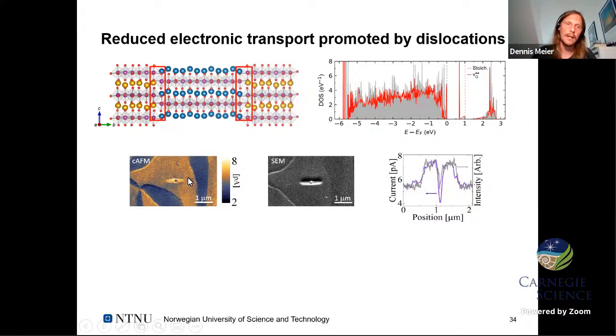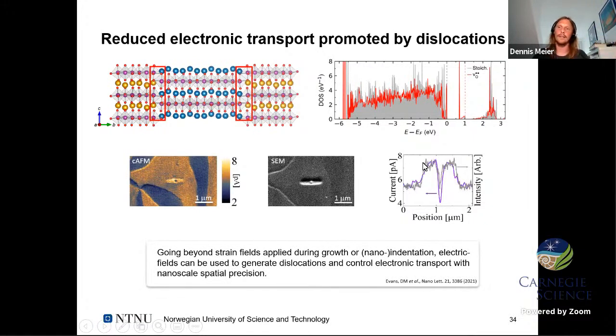And you can really see that when we now put an AFM tip, induce our dislocation or area with a lot of dislocations. At the very center, the conductance or conductivity goes down. You also see that with SEM, so it's not an artifact of the contact. And you see nicely in the cross section, transport properties go down. So by inducing dislocations, another type of defect, we can again play with the transport behavior of our material and thereby change the characteristics at the nanoscale.